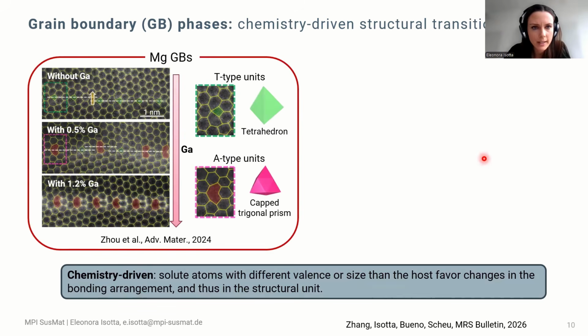Among examples in the literature of chemistry-driven structural transition is this one on magnesium grain boundaries, where it was identified that without gallium, the grain boundaries tend to show a tetrahedron structural unit, as you can see here. But upon the introduction of gallium, there's a progressive transition to a different structural unit, namely capped trigonal prism, which could be observed being gradual, as you see with the increasing amount of gallium.